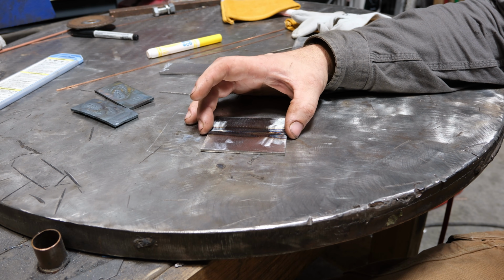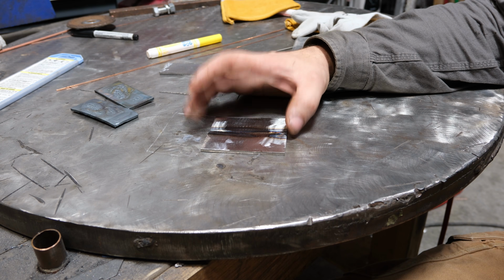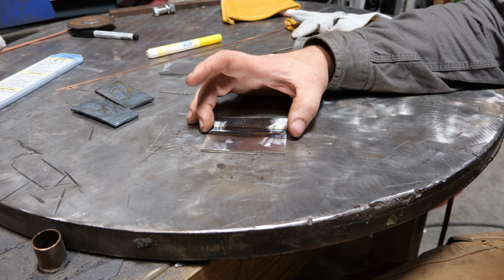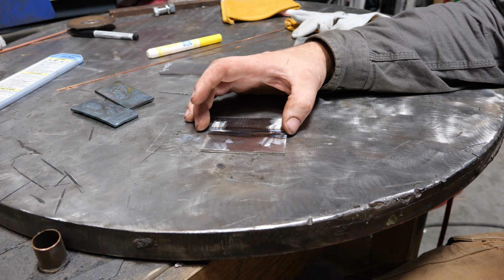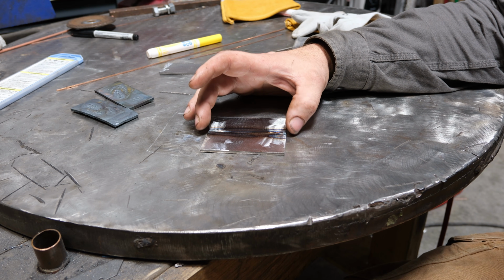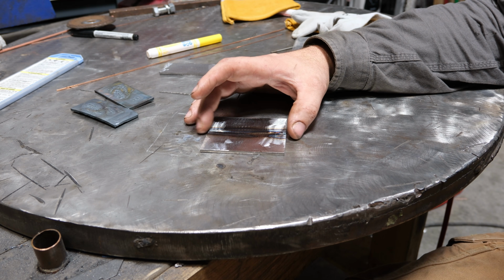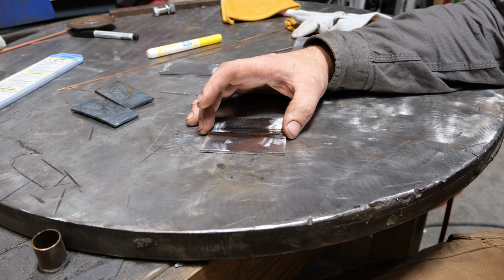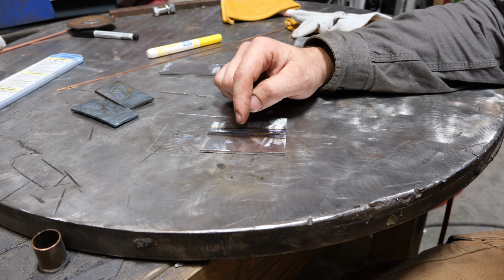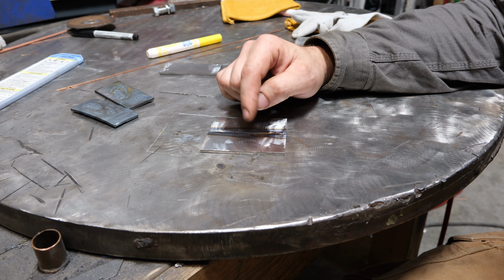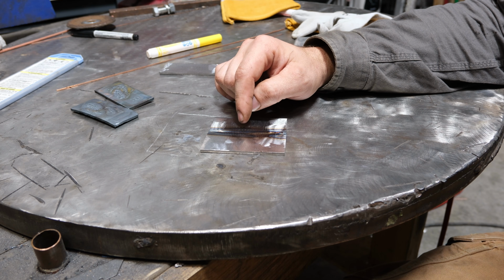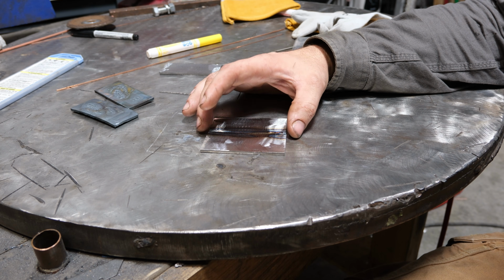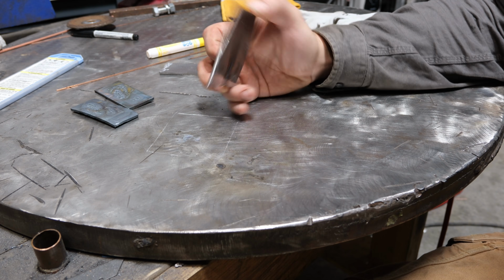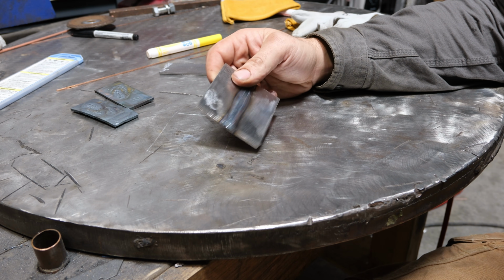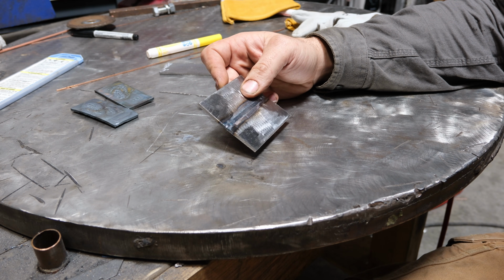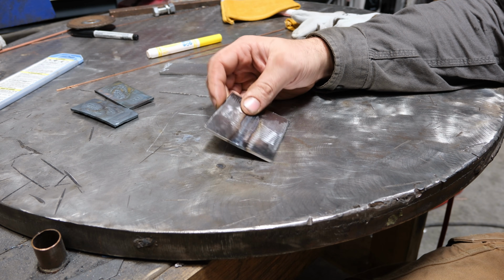And that is why adding filler and then running a slight gap will increase penetration, because the TIG process has basically no penetration whatsoever. I mean, very little. By running a gap and adding filler, we will be able to achieve in one pass more or less a weld that's approximately the thickness of this material, so that we have a strong joint. What we have here is not a strong joint, and I will prove it by cutting this in half, etching it, and let's look at what we have.